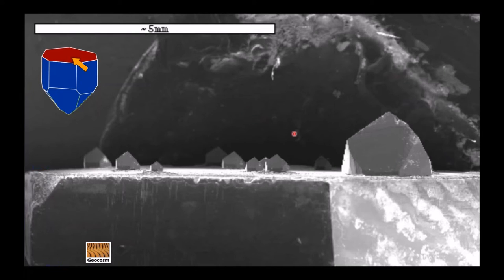So here we're looking edge on, and we can see that indeed, when we look at this large diameter hole here, this crystal grew considerably further away from the plate compared to this small one, which grew on a small diameter hole. So this seemed to confirm what we suspected from looking at the natural data sets. Now we have to, of course, answer why.